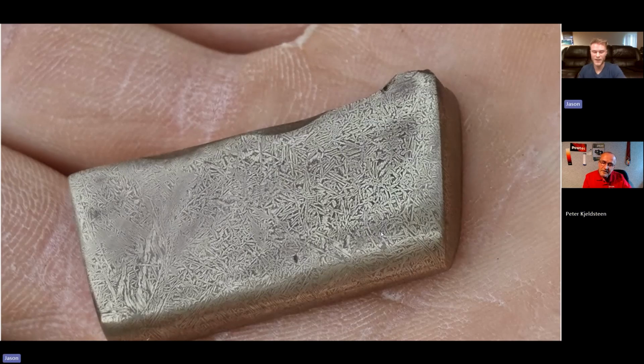Yes, that's correct. And so the way I did this was have the ingot and then cut it, polish it up a bit, and give it an etch in ferric chloride. Ferric chloride is going to preferentially etch the zinc-rich regions, and so that's the beta regions that you see, the darker regions. It also etches alpha, but a lot slower. And so the beta regions become depressed relative to the alpha, which is elevated.